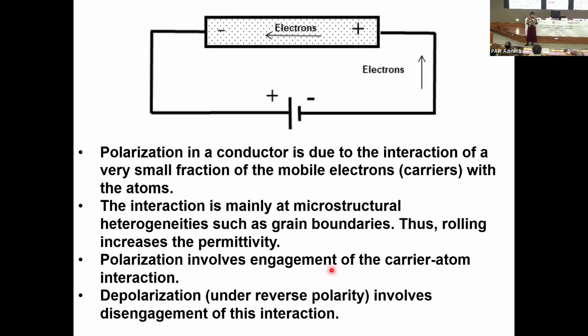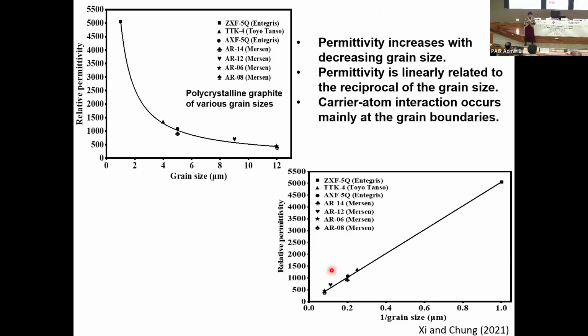So the polarization in a conductor is due to that interaction. And it involves a very small fraction of the mobile electrons with the atoms. And the interaction is mainly occurring at the microstructural heterogeneities, such as the grain boundaries. Thus, rolling increases the permittivity. And polarization involves the engagement of this interaction, whereas depolarization under reverse polarity involves the disengagement of this interaction.